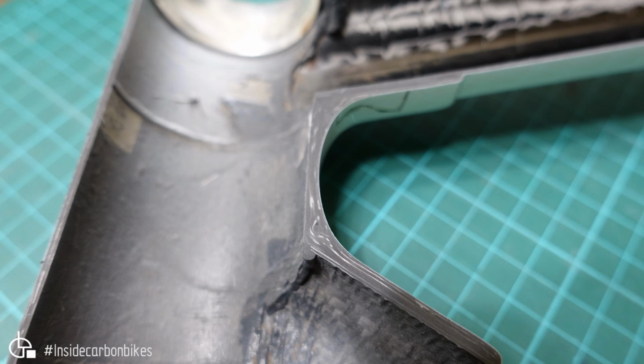So here you can see the wrinkles, so the fibre going like that. You've also got a bit of a void. So there's definitely something going on in this area with the head tube lug, because the other one had similar wrinkles and a larger void. The other one didn't crack, which is a little bit unusual considering the extent of the flaw, but from looking at both of these samples, you'd say that there's a higher probability that there's a problem with the production process in that region.